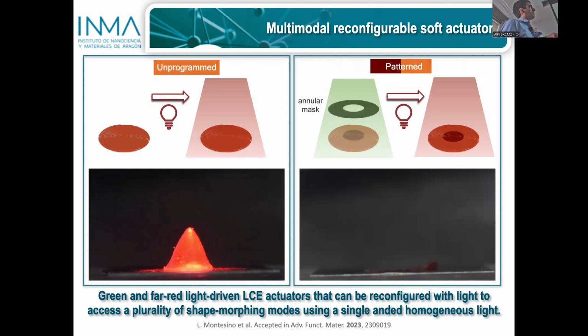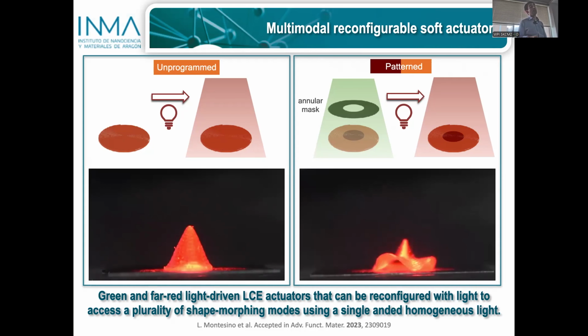But if now we pattern the material with this annular mask, we generate radicals in the central part of the sample. And if now we expose to far red light, what we get is a strong deformation in the middle that quickly generates a cone. But the outer annular part of the object cannot follow, and then generates these undulations along the azimuthal direction. Once the radicals are consumed, once the radicals go back to the normal state, the system recovers essentially the same configuration.